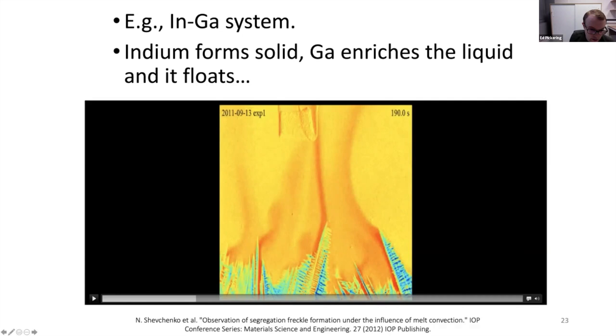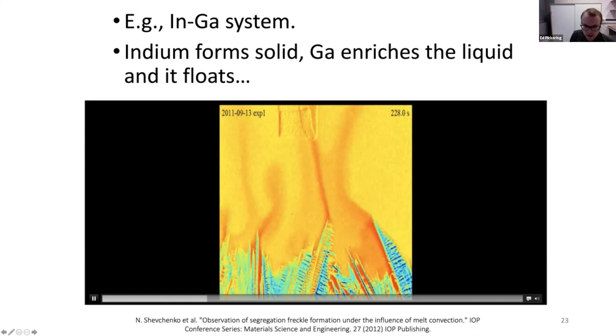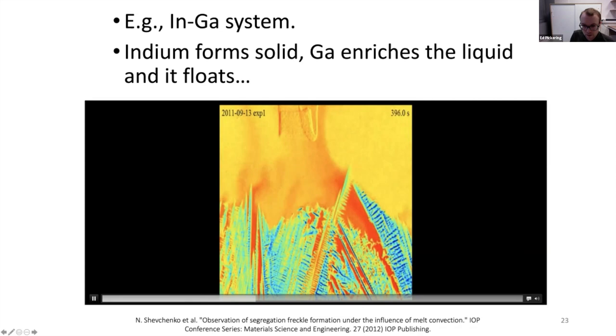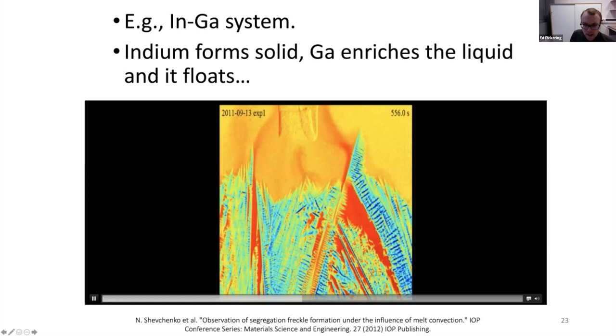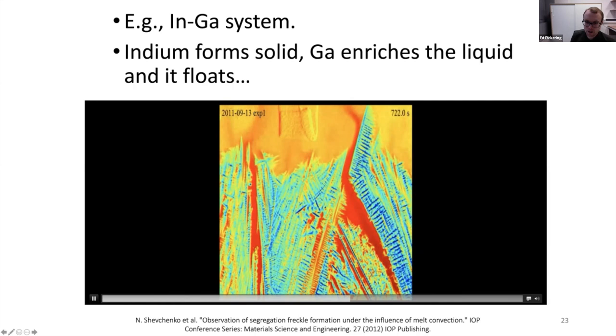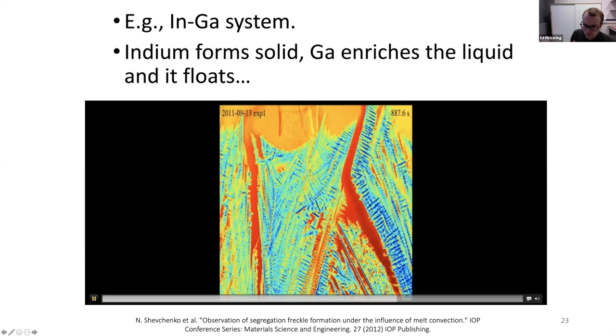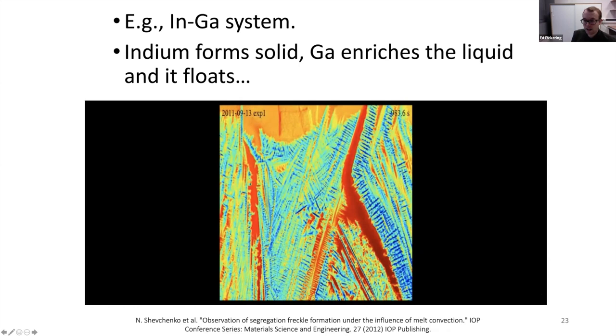solute-driven convection. And what you're going to see here is this dendrite, I hope you can see my arrow, my mouse, is going to grow across this channeled front here and is now going to be remelted by the flow of this enriched liquid through it. So can you see that? So you had remelting of the solid there, and all of a sudden you've got these beautiful channels, these deep veins of enriched liquid that are flowing up here through this particular very small indium gallium casting. But that's exactly the same way in which channels form inside massive steel castings, in fact.